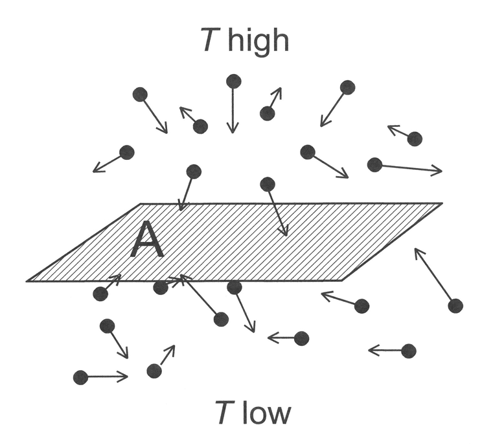The second approach is based on the relaxation time approach. Due to the anharmonicity within the crystal potential, the phonons in the system are known to scatter. There are three main mechanisms for scattering. Boundary scattering, a phonon hitting the boundary of a system. Mass defect scattering, a phonon hitting an impurity within the system and scattering. Phonon-phonon scattering, a phonon breaking into two lower energy phonons or a phonon colliding with another phonon and merging into one higher energy phonon.